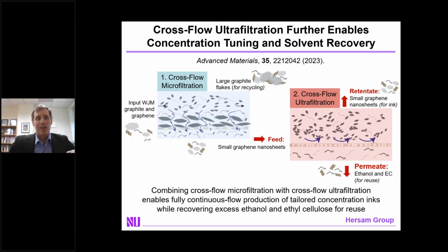But the issue is that it is typically a relatively dilute suspension, not one which you can directly plug into a printing methodology. And as a result, you need to do downstream concentration. And you'd like to do that in a manner where you can harvest and recycle the excess solvent, in this case ethanol, and any excess stabilizing polymer, in this case ethyl cellulose. And that's done with a second cross-flow filtration step. This one is called ultrafiltration, where now the pore sizes on your filter are smaller than your nanosheets, and as a result, the nanosheets go down the axis of the cylindrical membrane. And what's pulled out in the cross-flow direction is the ethanol and the ethyl cellulose, giving you a permeate stream which can then be easily recycled, concurrently controlling the concentration of the dispersion to get suitable viscosity for printing.